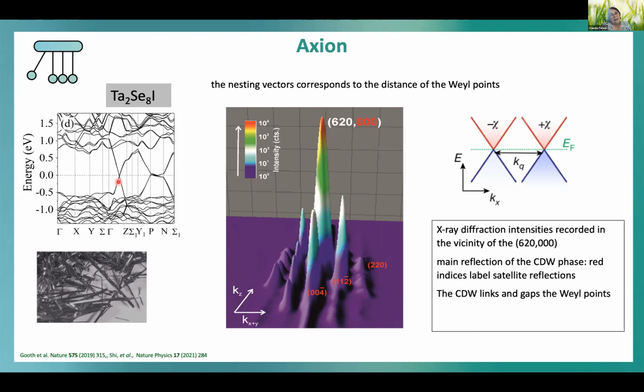So it might be, I think, that especially systems which have Weyl crossings at the Fermi energy, which are very clean and have no additional bands with electrons and hole pockets, might be very easily destroyed by correlation and go into such a charge density wave phase. So therefore it might be interesting to look for more charge density wave systems and to look whether there's a connection to axions, phasons, and Weyl semimetals.